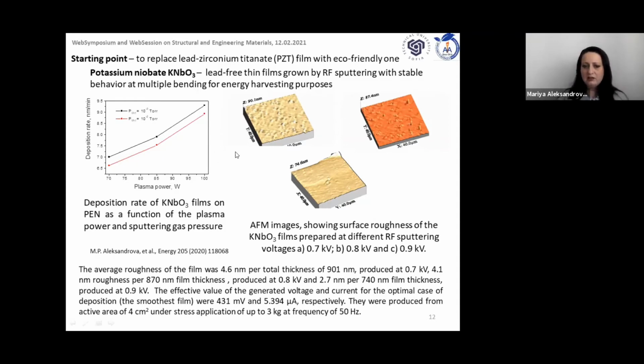Here it is shown what the relation is between deposition rate and some deposition parameters like plasma power and sputtering gas pressure. And here are some atomic force microscopic images showing the surface roughness and how it is related to the deposition conditions. So we succeeded to produce a surface which, according to the AFM measurements, has 2.7 nanometers RMS surface roughness, really smooth.